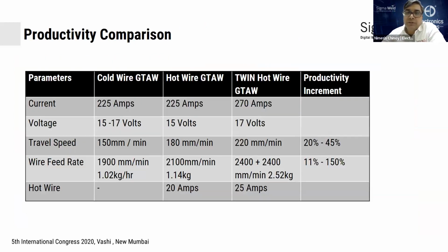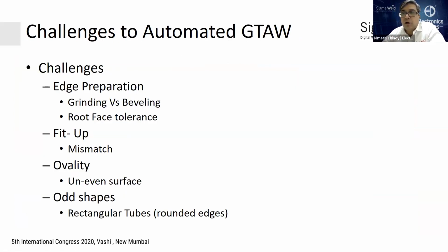And in those cases, if you use twin wire with hot wire power sources, 150% improvement in deposit rate. This is something that you can use. It's largely used in cladding applications where a lot of material has to be deposited.